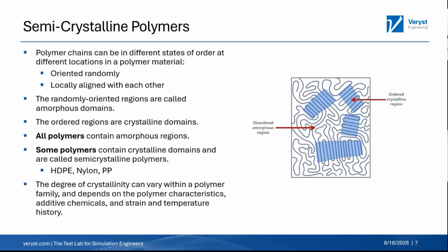So I'm going to start by talking about crystallinity in polymers, because I like this diagram that you can see over here on the right hand of your slide, which I like to call the spaghetti structure of polymers. It's generally a good mental model for what polymers look like: every polymer chain is this extremely long molecule, generally linear, but not always. But it's useful to think of them as spaghetti strands that are all mixed together, all jumbled around. There's not a lot of local order to the polymer chains, in contrast to other engineering materials like metals, where there's a very specific crystal structure. The atoms are in very specific repeating spots that give rise to the interesting properties of metals. But polymers are different because there are some polymers that have no regions where there's any local order in the polymer chains at all, fully amorphous polymers.